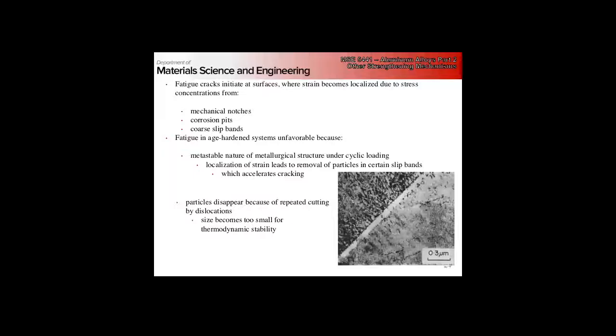So this is just an image here of a slip band in a grain. You can see through the repeated ratcheting, we've completely denuded the slip band of any precipitates in there. So this band is now significantly softer than the surrounding neighborhood, which means that flow is just going to keep happening there. It's also becoming cold worked, so it's losing toughness, losing ductility. But even with that, it's still significantly softer than the surrounding area.